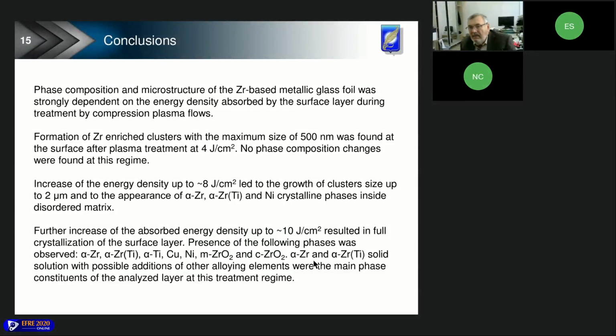Well, though we're just in time, the conclusions of this work are summarized here on the slide. But in conclusion, I'd like to say the following. The idea that the metallic glass will remain in a disordered structure during cooling from the melt after plasma impact with the treatment parameters used didn't work in our case.